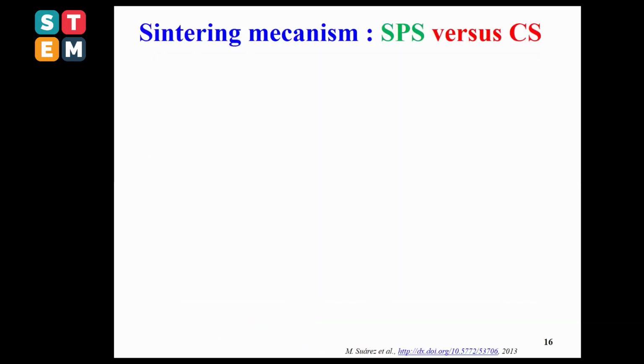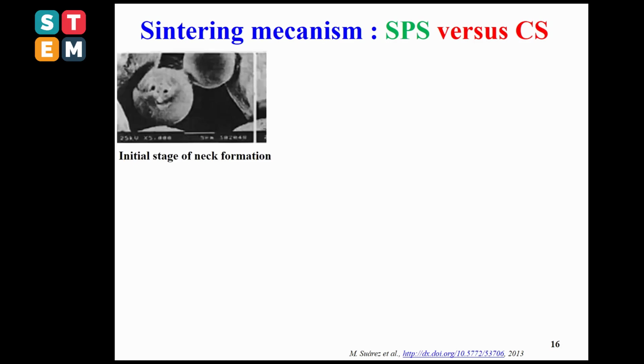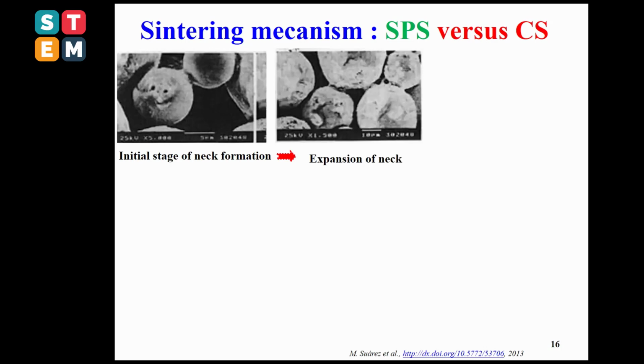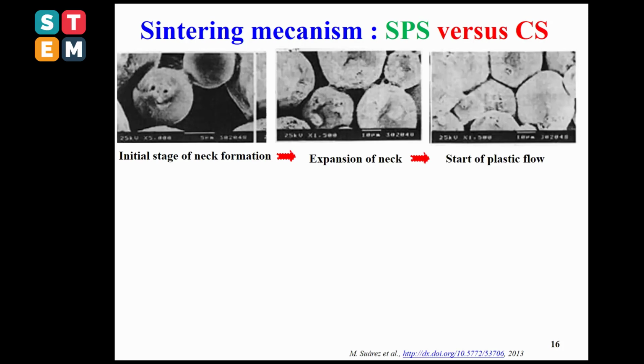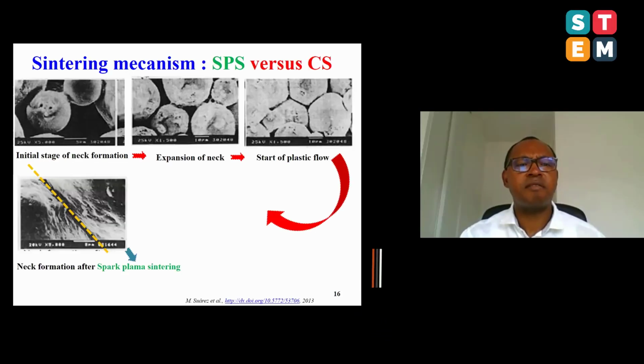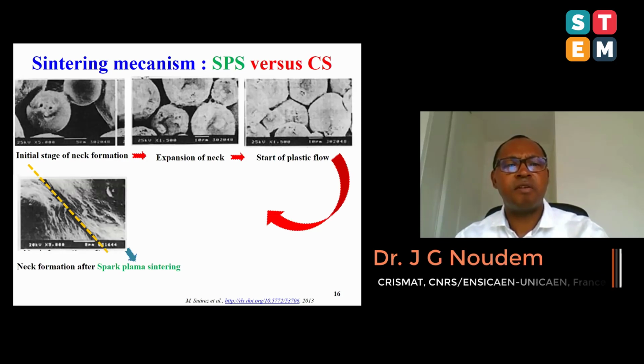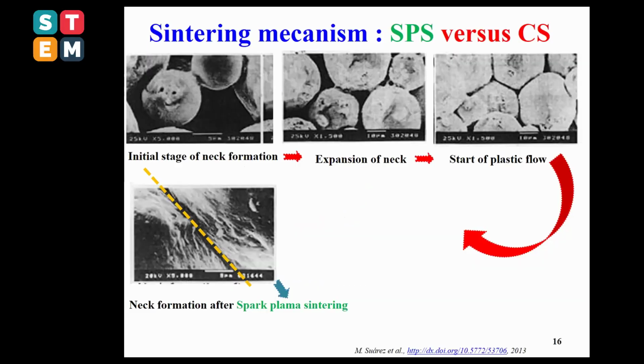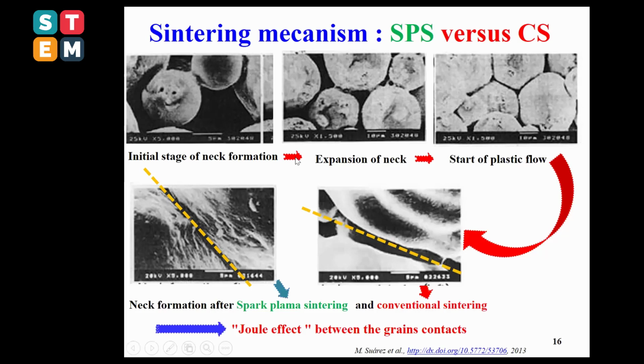And how is the sintering mechanism, SPS versus what I call here conventional sintering? You can clearly observe here in the initial stage, you have some neck formation. And then the expansion of this neck in the next step, and then the plastic deformation. And at the end, you can clearly observe the neck formation between two grain boundaries in the case of SPS. If you compare with the conventional sintering one, you have again this neck formation in both cases. This again confirms the Joule effect between the grain contacts.